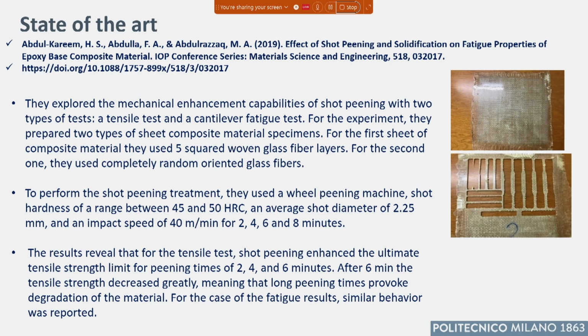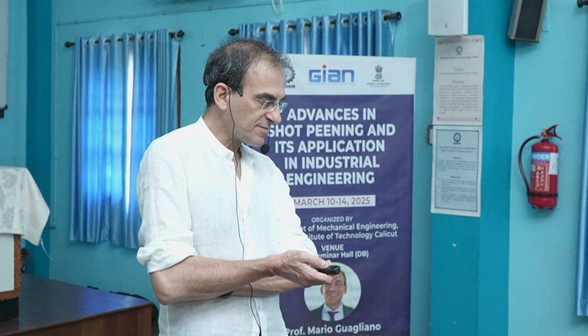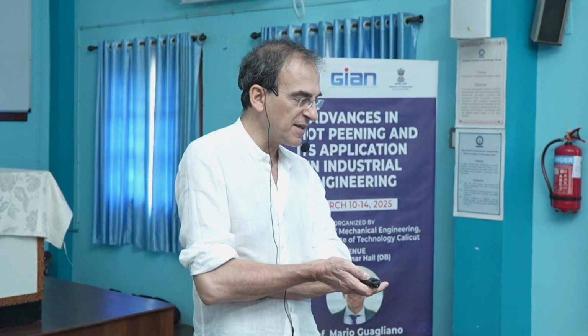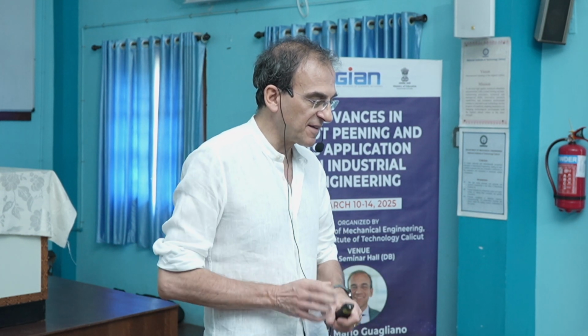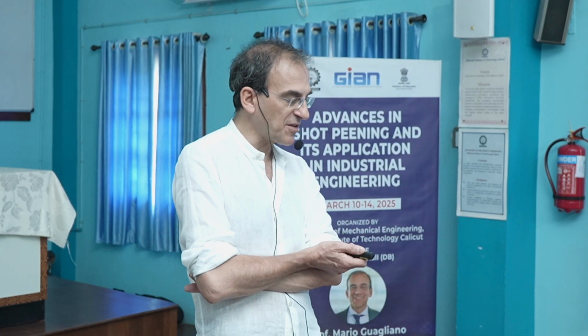And the results are these. The shot peening is able to improve the fatigue strength for the treatments with 2, 4, and 6 minutes duration. After 6 minutes, indeed, the strength decreases. It means that we are in the overpeening case for this kind of material. So by considering this paper, we see that also for this kind of composite material, we are able to use shot peening for improving the fatigue strength, but at the same time, we should carefully manage the design of the treatment, the duration of the treatment, otherwise overpeening is possible.